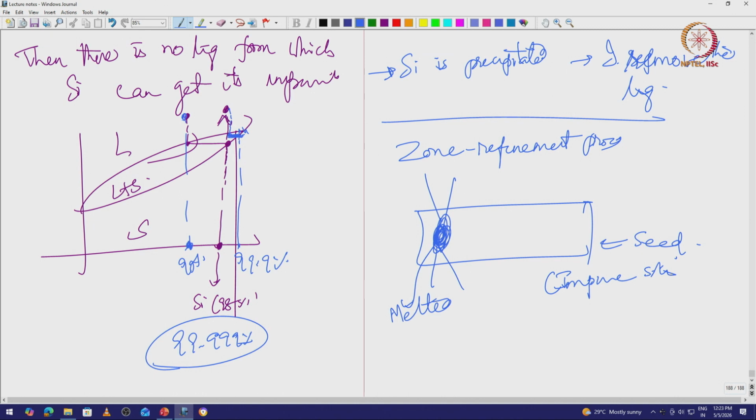So, now you have to cool it, and the way you cool it is you either move the solid or you can move the source. So, you move this melt away. Essentially by moving the melt away, you are cooling down that region. So, that region, let us say I have moved the solid, very slow movement.